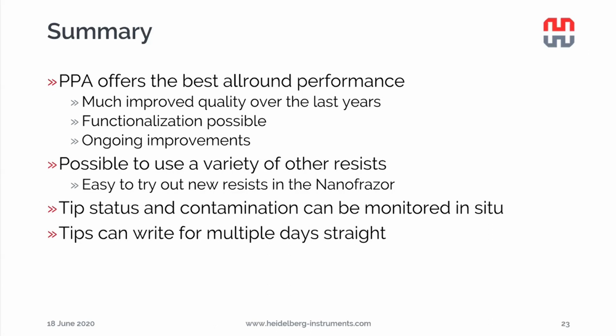You can also use a variety of other resists, quite easy to try in the NanoFrazor. Give us a sample, put it in the NanoFrazor, see if you can pattern. It's quite fast. Then we can measure the tip status and the contamination in the tool itself. You don't need an SEM for that, and you get direct feedback on how well your patterning was. And the tip endurance is also quite good now. We can write for multiple days straight. I started some experiments on a Friday, and it was still running on Monday when I came back. So this is also quite nice. So that sums it up.